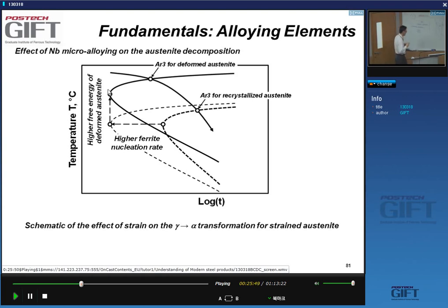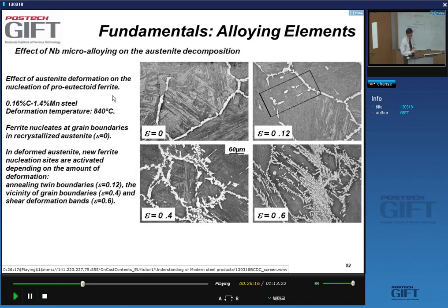And you know that the driving force for the transformation is the difference in free energy between austenite and ferrite. When you deform the austenite, you increase the free energy of the austenite, and in other words, you increase the delta G, the driving force for the transformation. This is why the C curve moves left and up. Okay? And you can see this, again, by doing the trick I explained to you here,